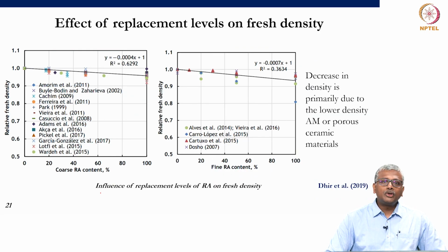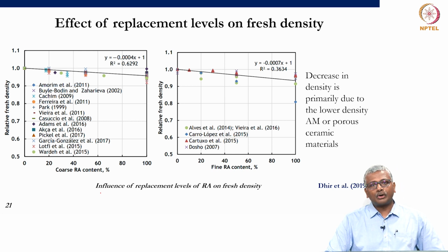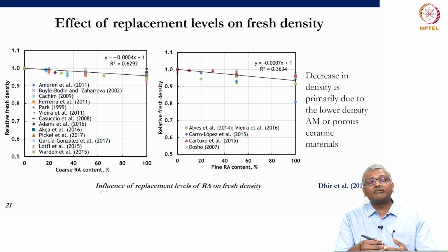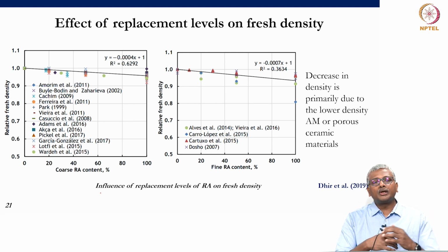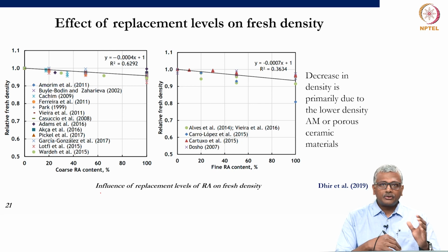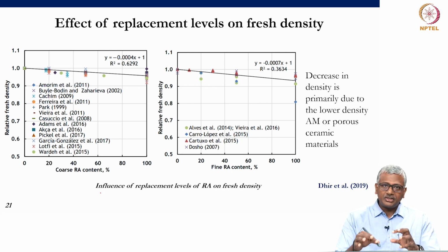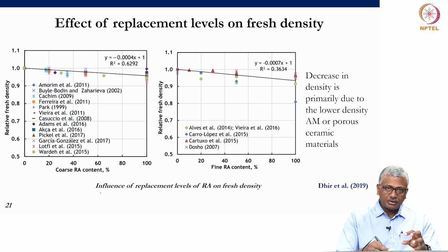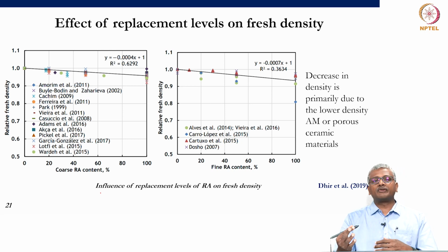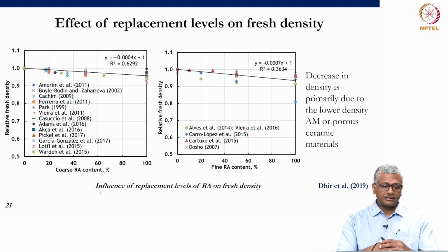Now, when you replace conventional aggregate by recycled concrete aggregate, it is expected that the density of the concrete will drop. Why is this? Because adhered mortar is present, there will be water absorption, there will be higher porosity because of the water absorption and so on. Of course, water absorption is not the critical factor for density, it is more the porosity introduced by the adhered mortar that will lead to the lowering of the overall density, right. So, you need to be aware of the fact that your density will change when you replace conventional aggregate with recycled concrete aggregate. When you do better processing of your recycled aggregate, obviously the differences in density will not be that significant.